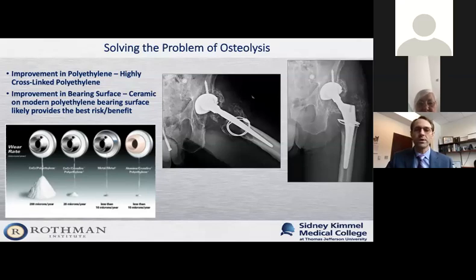Therefore, in the early 2000s, companies began offering highly cross-linked polyethylene that has essentially gotten rid of the problem of osteolysis and polyethylene wear. In fact, it has been so successful that I'm likely the last generation of orthopedic surgeons who will have treated patients with polyethylene wear-induced osteolysis. Then we've also found that what material we use on the ball also has an effect on the wear rates, with a ceramic ball articulating on a polyethylene liner having incredibly low rates of wear.